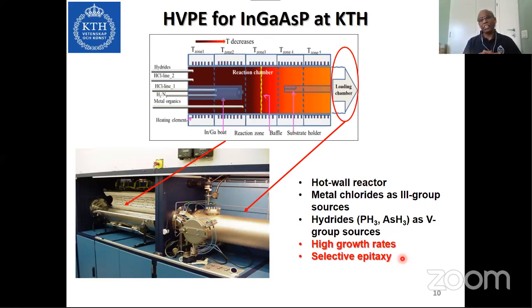Now, this technology has a very high growth rate, and it can also grow very selectively at certain places where the wafer is masked. It will not grow on the masked region, but it will grow only on the open area. These are the two things which we use actually. So we cannot compete with MBE or MOVPE to grow nanostructures or quantum wells, but we can grow very thick layers, and that is where we exploit this technology for fabricating very advanced devices. Of course, we cannot make these advanced devices only by VPE. We need the basic structures grown by MOVPE and MBE.